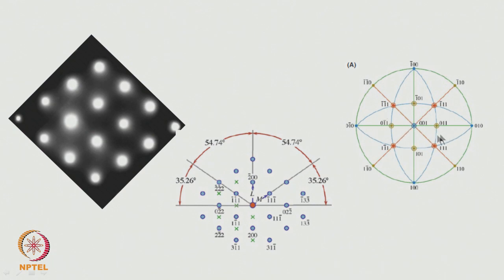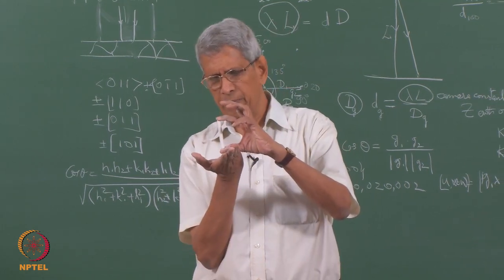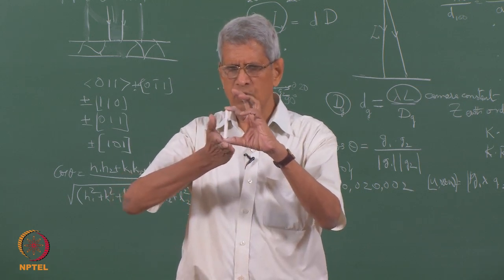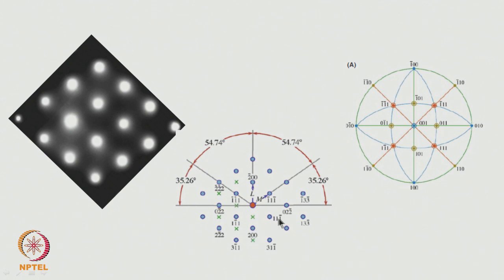From this you can understand that using stereographic projection we can index the patterns correctly. Suppose the sample is tilted in a different direction — the beam direction will change. If a different zone axis is reached, the indexing of the spots will change: for example, what was 200 may become 111 and 022. This change in indexing with tilt direction is very important in defect analysis.